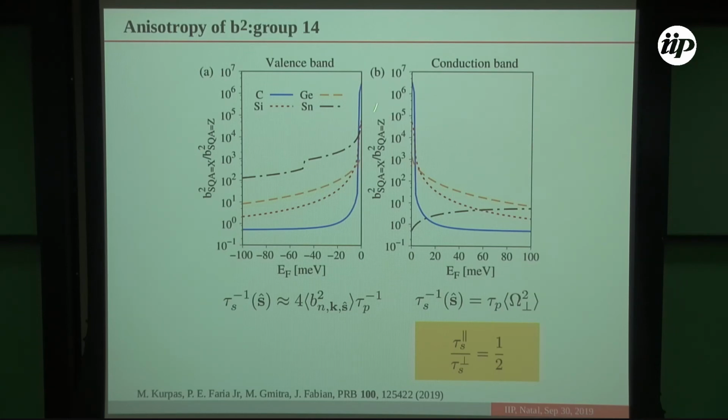But then you see that this ratio is not 1/2, because the ratio of the anisotropy is then 10^6, let's say, in to out of plane. The same would happen for Dyakonov-Perel, because there are also spin hotspots in Dyakonov-Perel. So I would say they would follow the same dependence, and you would not be able to distinguish, as you said, which one is which. But what if you look at the temperature dependence of the ratio? Okay, then that's the key, I would say. How it follows the momentum relaxation time, then you could distinguish from these basic formulas I showed, right?